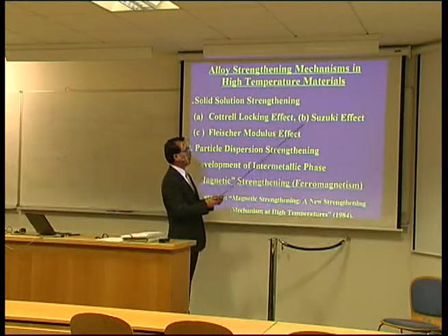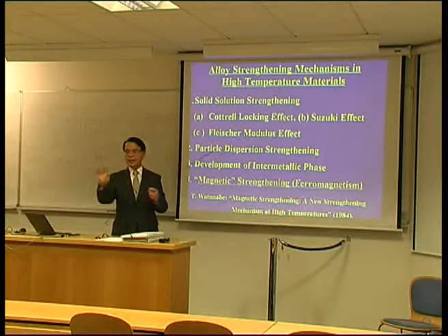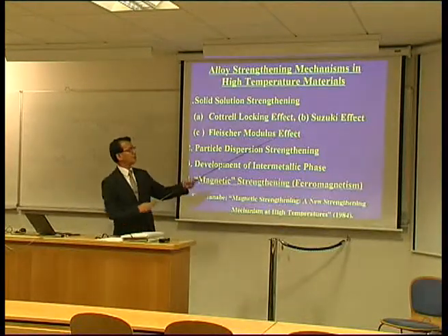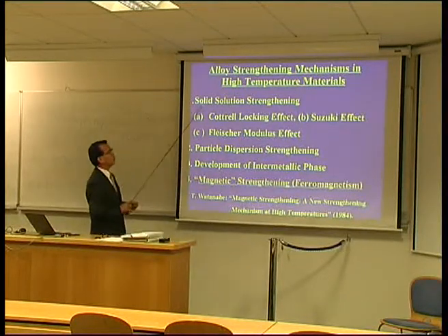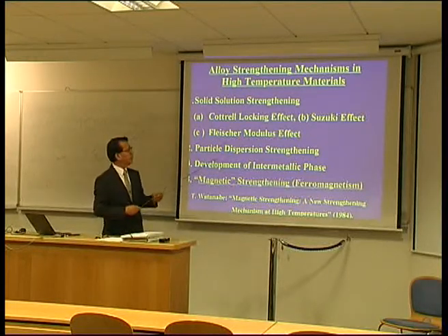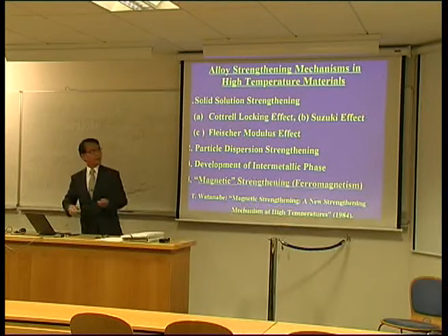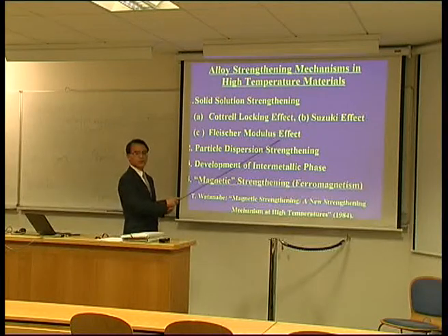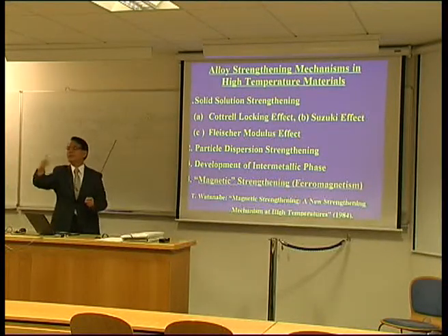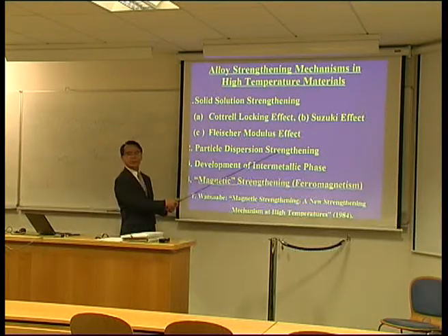And second, in the case of an FCC alloy, by adding another element, the stacking fault energy can change, so two partial dislocations separate more extensively. That's called the Suzuki effect. This is a second source of solid solution strength. And if the shear modulus of the solute is different from the solvent, we can expect a shear modulus effect. And also, by putting particles in the matrix, when a dislocation moves in the slip plane, particles pin the dislocation motion, so we can get particle dispersion strengthening.